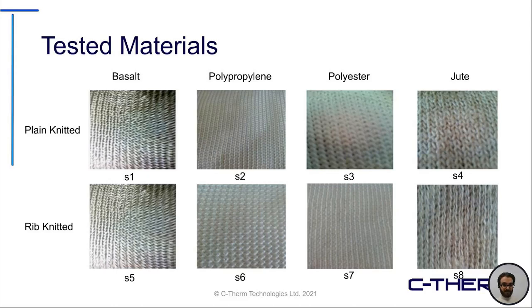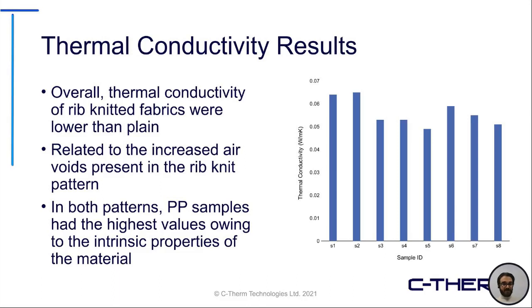So they had four different test candidate materials, each with two different knit structures. And they were looking to see, obviously, how these different materials performed compared to each other, but then also how they compared overall when looking at the different knit structures and patterns themselves. Really, at the end of the day, using thermal conductivity as the overall guiding metric here, they were able to determine that the ribbed knit structures were lower than the plain, therefore having a warmer feel or cool touch if you relate that to the thermal effusivity of that sample. You can understand this based on the fact that the increased air voids that would be present in the rib knit pattern as compared to the plain would influence your overall thermal measurements.